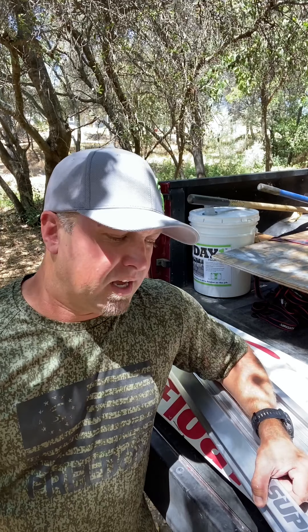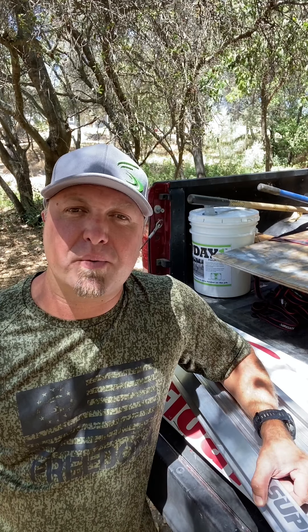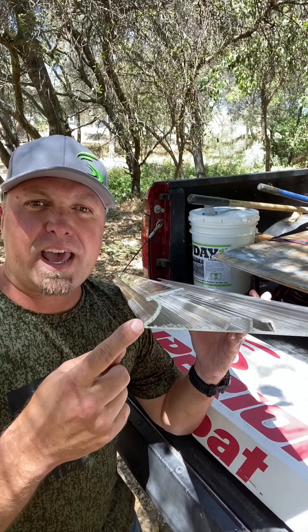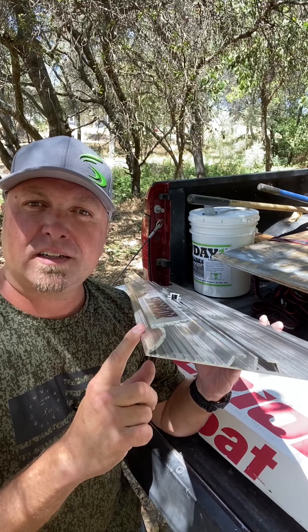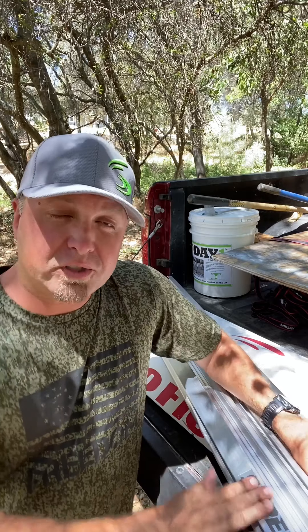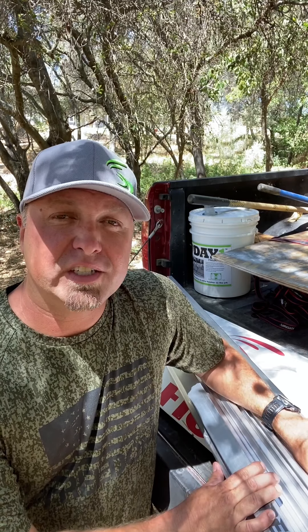If you want to leave it open, just leave the cutting edge on the back side. When I personally pour concrete, I run it with the cutting edge towards me after we hand rod it, cutting out any high spots. What's unique is when you cut a high spot, that excess will roll back onto the concrete rather than going up over the float. So when the cutting edge is facing you, it's going to leave the concrete open.